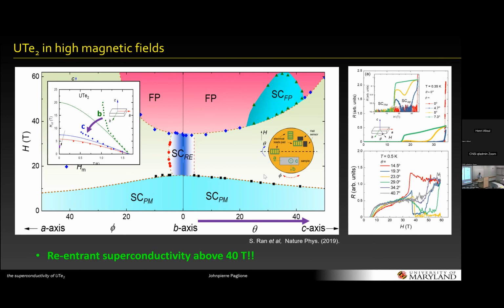Sorry, I don't have the data here, but if you look at, this is resistance, but if you look at TDO data, so if you go up in field and look at this field polarized state transition, the TDO data changes abruptly in the direction that you would expect for a ferromagnetic, like a magnetization increase. And in this superconducting state, it goes the other way. It looks diamagnetic.